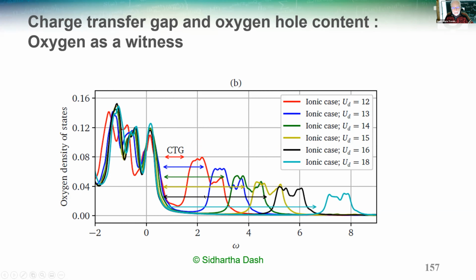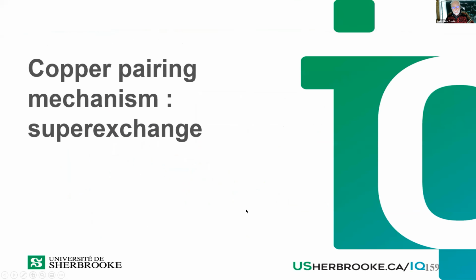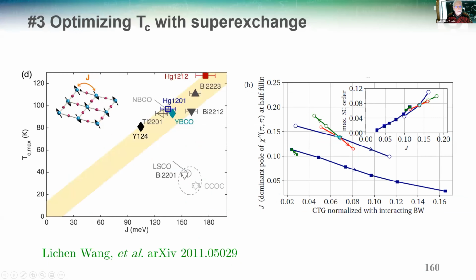And what I said is that to optimize TC, you need a small charge transfer gap. So you need a large oxygen hole content. So you see oxygen here is sort of a witness of the charge transfer gap. Now let's go to the pairing mechanism. That takes us to the third example, but perhaps there are questions here. Okay, so go on the right-hand side.